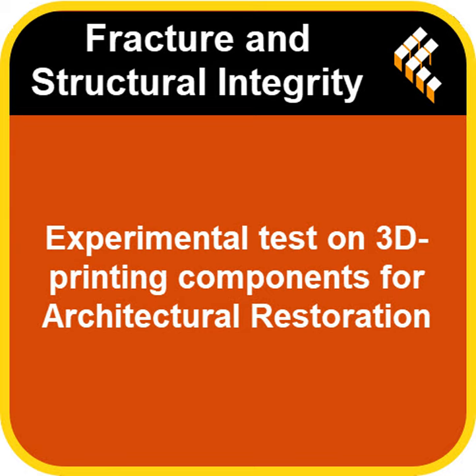Low variation between samples. Which is good if you want reliability. Absolutely vital if you're thinking structurally. Now, for the truss beams under tension, the pulling tests, they saw what's called elastic brittle behavior. Meaning they stretched predictably under load, that's the elastic part, but then failed suddenly once they hit their limit, the brittle part. No slow yielding or stretching before breaking.